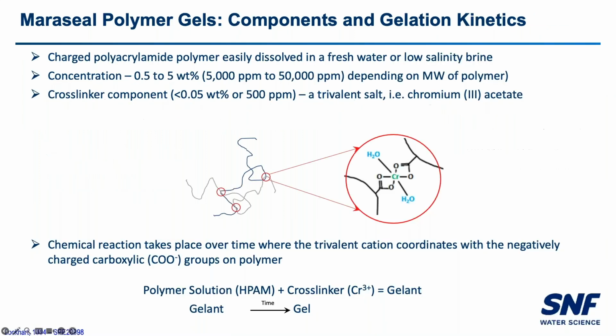Next slide, please. So in terms of how the Maraseal gel is formed, as mentioned, we've got roughly 5% hydrolyzed polyacrylamide, easy to dissolve in any field brine. Concentrations used might be between 5,000 and 50,000 ppm, depending on the strength and the quickness of the gelling that we want. For the most part, we're using chrome 3 either in acetate or chloride form, again depending on the speed of the reaction. In the schematic here, you've got two polymer molecules. Through that carboxylic acid functional group, we can get chromium coordination. Once you have a certain number of coordinations formed, you get a more and more rigid structure. So we move from a very flowable gellant into a more rigid gel structure that can resist water flow. Next slide, please.